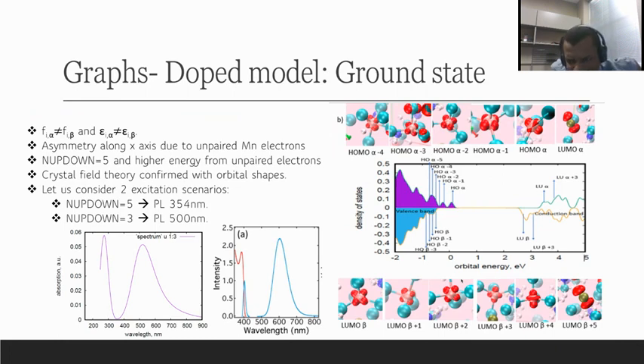Besides that, the difference between the HOMO alpha and the LUMO alpha is about the same as the undoped model. But if we allow this electron to have a transition from the HOMO alpha to the LUMO beta, then the difference between these two energies would be about 2 to 2.5, and that would predict a PL of at least 500 to 600 nanometers.